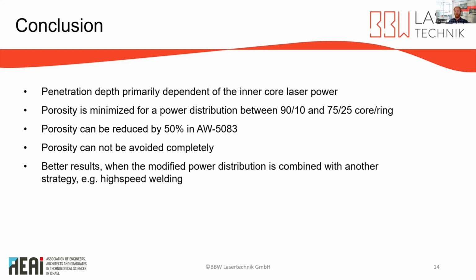Since pore formation predominantly occurs at the bottom of the keyhole, the application of flexible power distribution porosity can be reduced but cannot be avoided completely. Here we must combine this strategy with another strategy. The results show that penetration depth is also primarily dependent on the laser power of the inner core due to a much higher intensity, and it is assumed that the reason for the reduced porosity is therefore a reduced vapor velocity due to an increased keyhole opening.